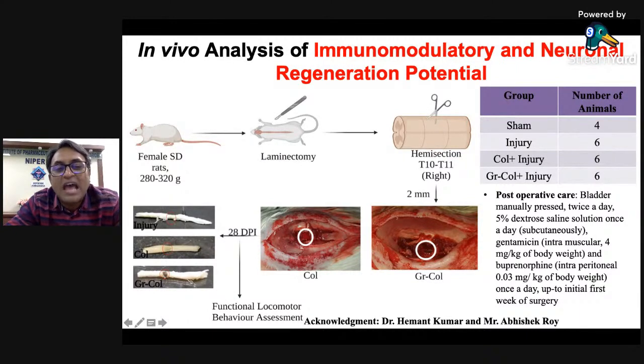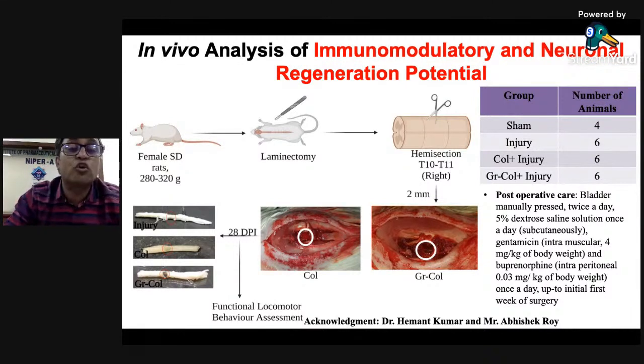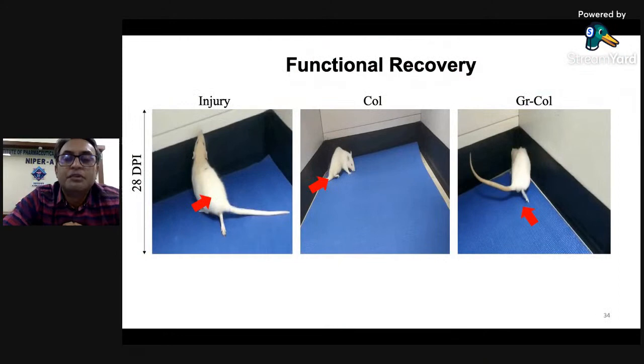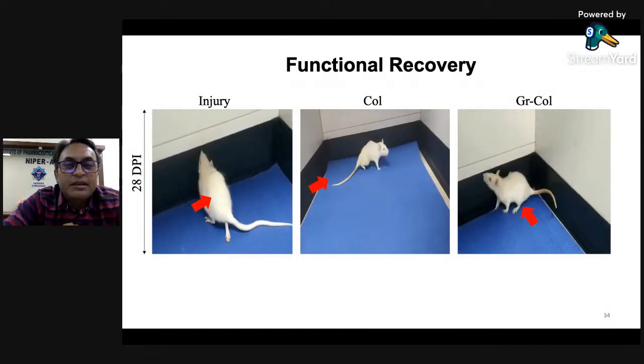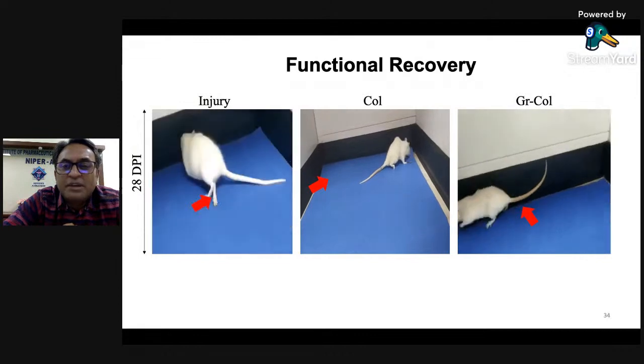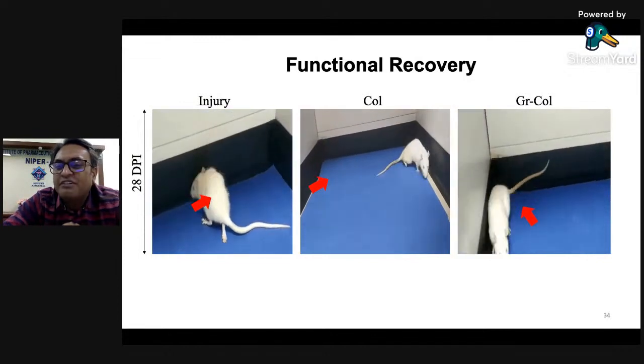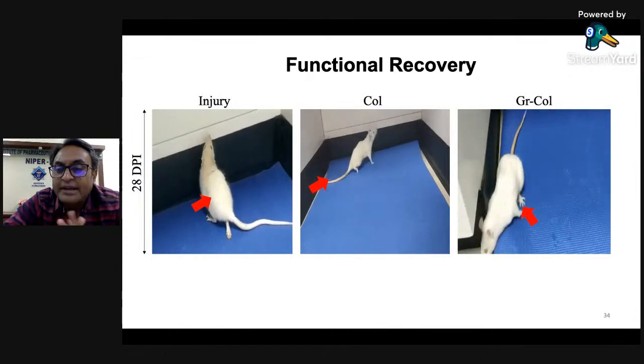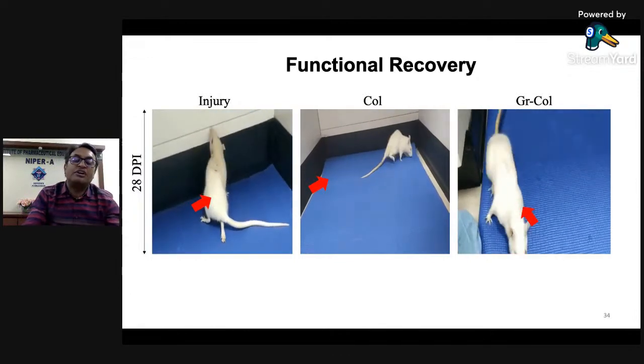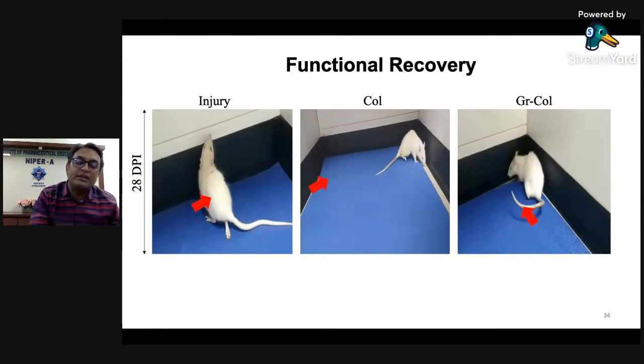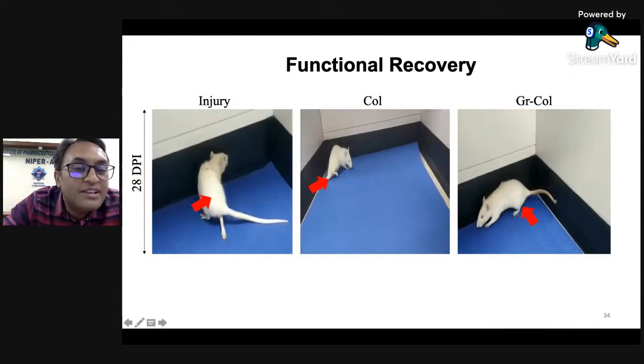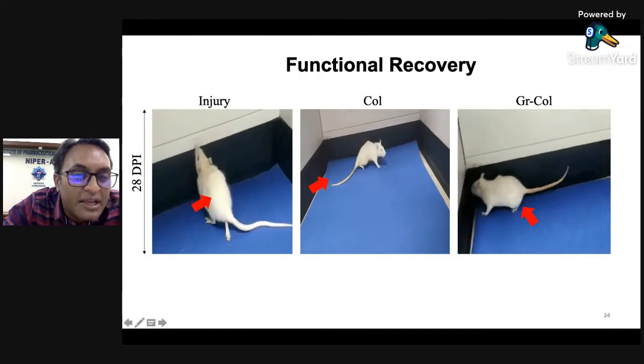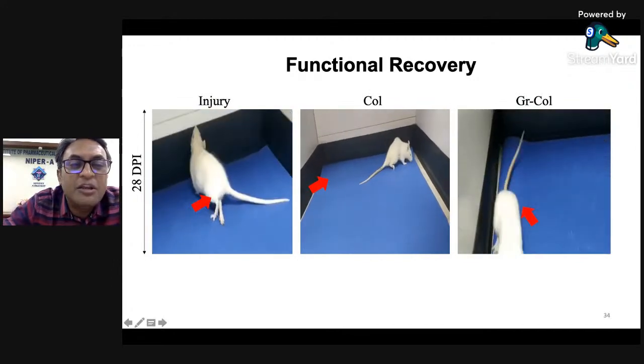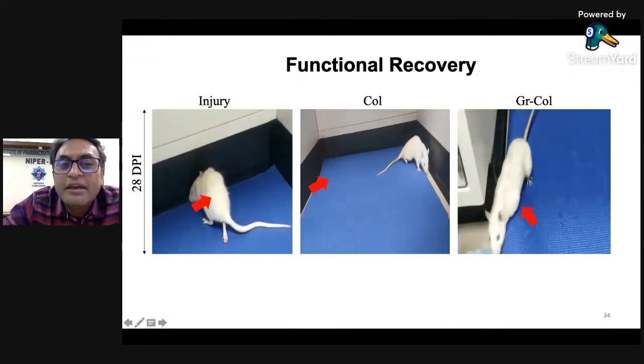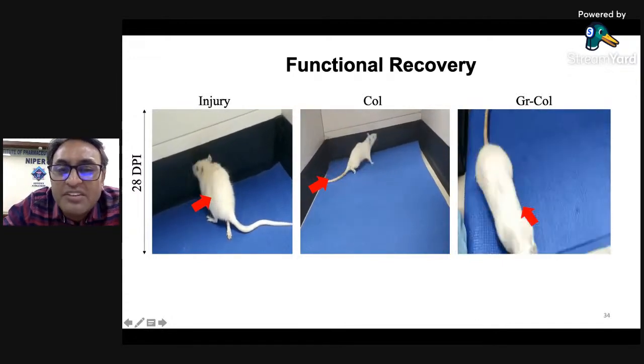We first tested what happens to the animal, particularly their locomotory behavior. We were very surprised to see that the Gr-Col material actually recovered the entire locomotory function by day 28, though it was already retained at day 14. In the injury area, the right back leg is paralyzed and the animal walks with only 3 legs. With collagen implant, there is some recovery, but it is still limping.